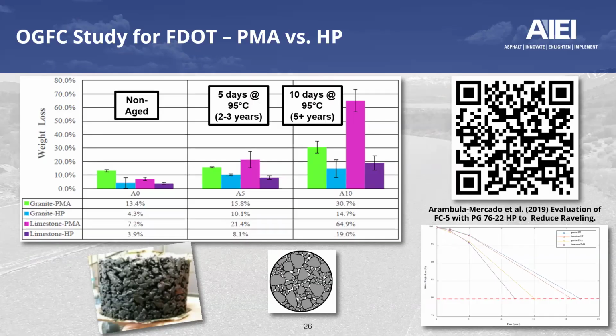I don't know if either of you might be able to add anything to that, helping out Alabama and Florida. So the only thing that I may add is when it comes to high polymer technology, there are two distinct ways of approaching the mix, whether it's open graded, density graded, or even SMA. For example, Virginia DOT uses SMA with HP. They designed their mix using the conventional way of designing the mix, and then they just do a binder swap, and then they get that extension in performance life. And we've seen that in the case of Florida DOT with the open graded friction course, and it showed a significant extension in performance life.